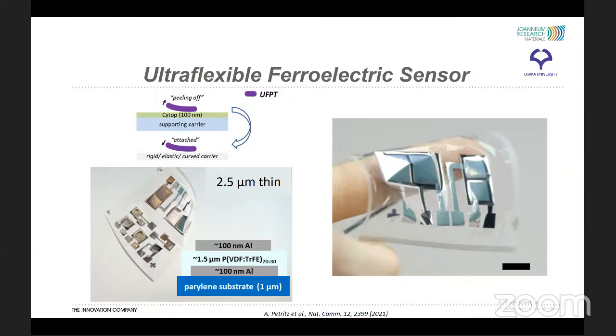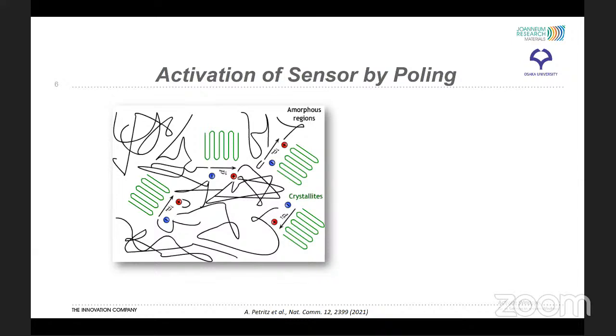compliant to the skin. The sensors are based on a solution-processed thin PVDF-TrFE layer sandwiched between aluminum electrodes and fabricated via a foil-on-carrier technique. The ultra-flexible sensor foil can easily be detached from this carrier and later on attached to other substrates and, for instance, to 3D-shaped objects like the human skin. In this context, it is also important to mention that PVDF-TrFE is a semi-crystalline polymer.